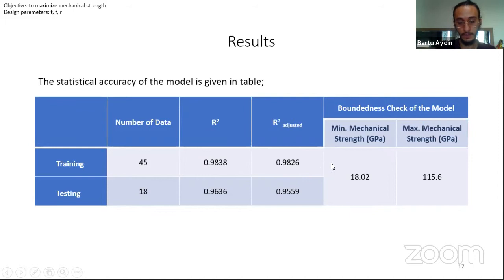But in order to determine whether our fitted regression model is bounded or not, we carried out a boundedness check of the model by checking the maximum and minimum values in the search space of design variables specified in this study. The values of strength are obtained as 18.02 as a minimum and 115.6 gigapascal as a maximum. Since the model gives realistic results in the manner of engineering, it can be interpreted as bounded for this study.